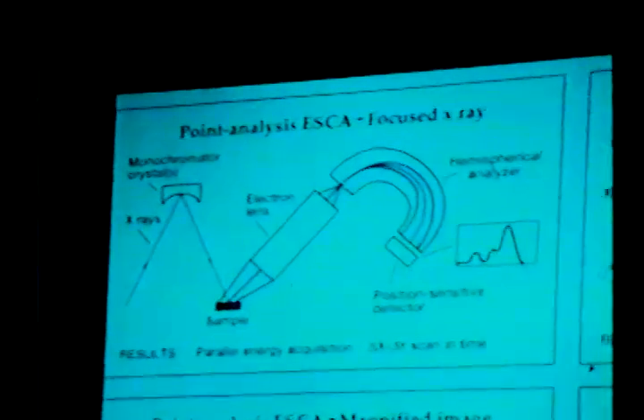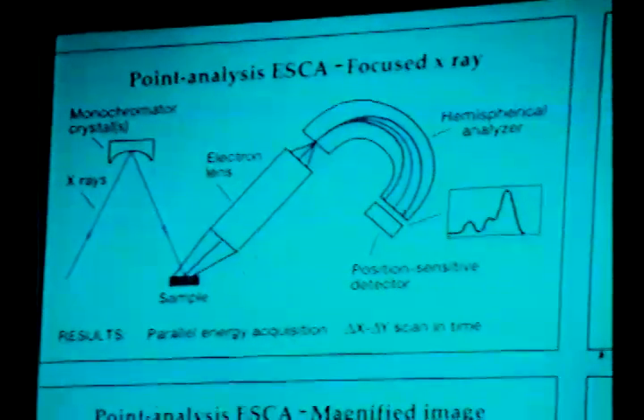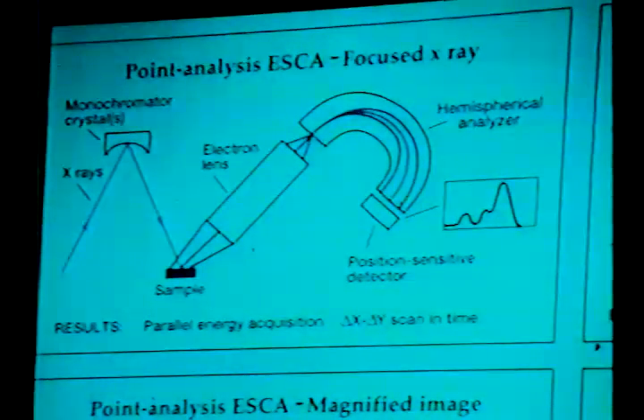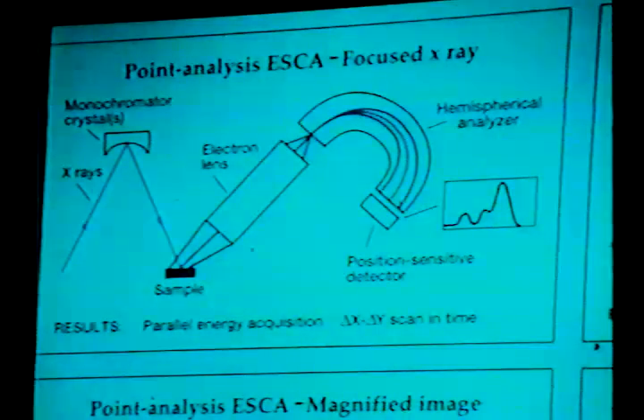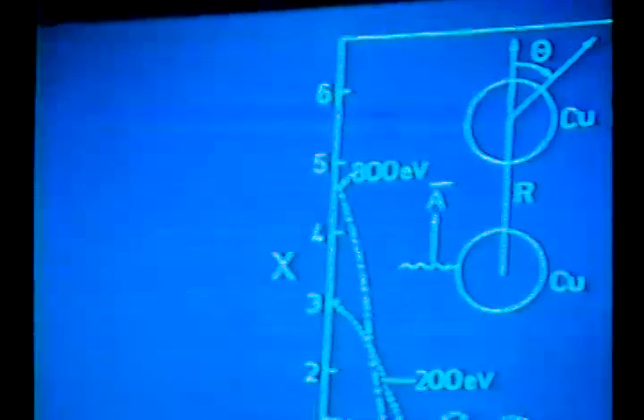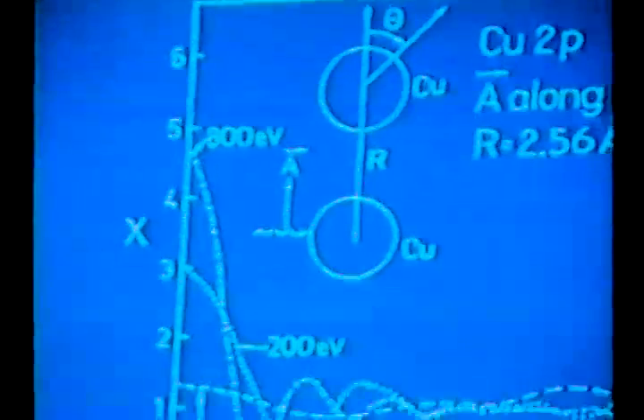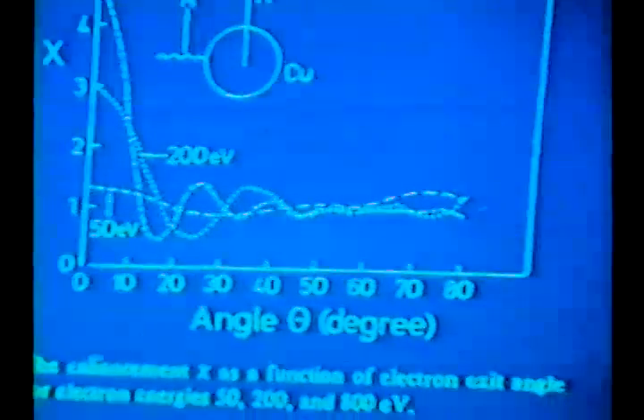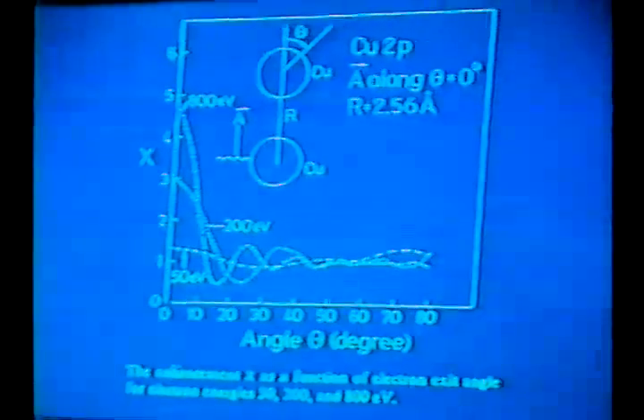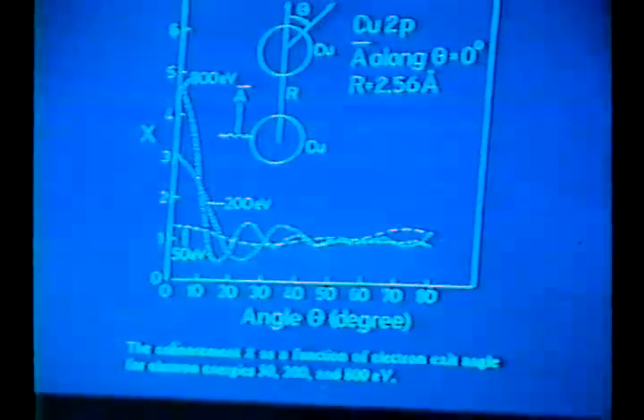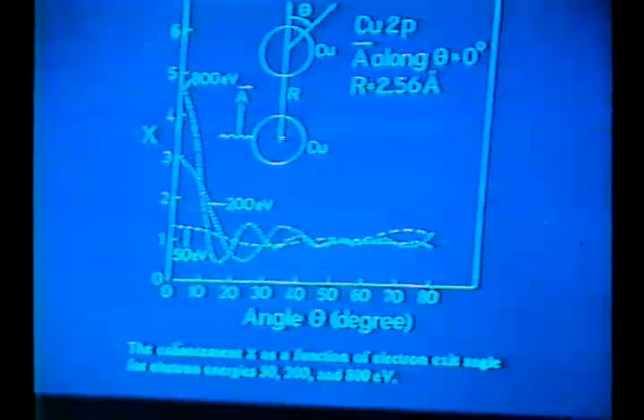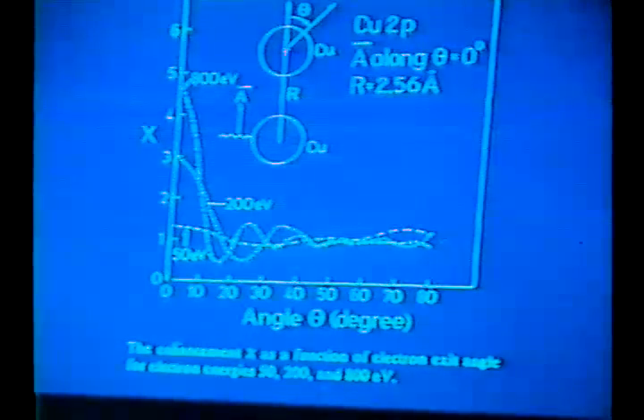Of course, in this limited time, one cannot cover the whole field in generality, but I'm going to try to cover some new aspects of electron spectroscopy. It is possible now to do ESCA on very small spots, including angle resolved both core level spectroscopy and valence band spectroscopy, by rotating the sample, with very high energy resolution, very high for XPS, about 0.25 electron volts, and with peak position to hundredths of an electron volt. So it is now possible to work with very, very small single crystals in ESCA and get all the information that is contained here and more. I'm going to concentrate on structural information first.